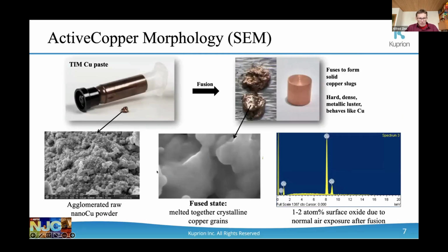When you dig deeper, looking at the nanostructure, it is a nanomaterial. We have nano copper in there that's at the core, and it's heavily agglomerated. So it already comes from the beginning in this paste form. And when you fuse that, it all fuses together at a relative low temperature, about 80% below its actual melting point, to more or less solid copper. And all the additives and surfactants, they evaporate during that fusion, and you're only left really with pure copper. So a very good material to replace solder with much higher performance thermally and electrically than with solder.